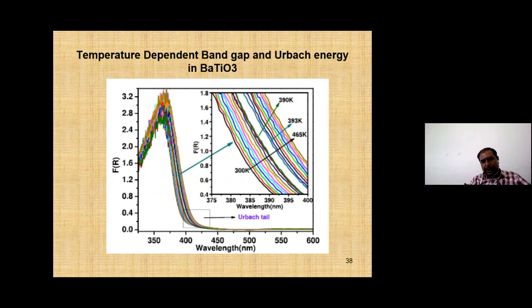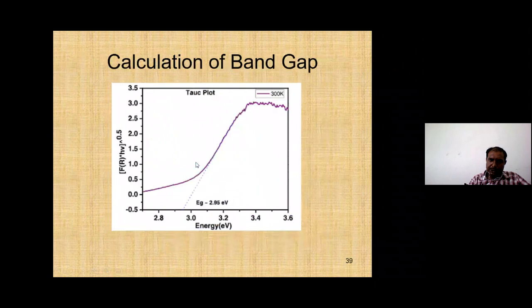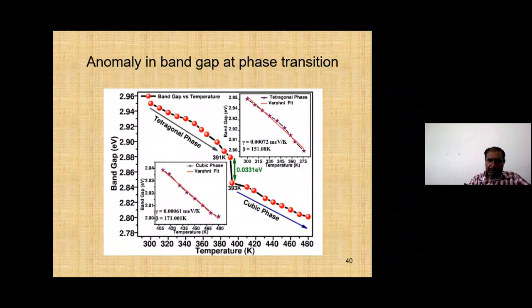And what we have done is that we have measured the optical spectra as a function of temperature. Using this spectra, we have estimated the band gap, and then we have plotted the band gap as a function of temperature. So you can see that when you increase the temperature, the band gap is systematically decreasing, and at the point at which the sample goes from tetragonal phase to the cubic phase, there is a sudden jump in the value of band gap.